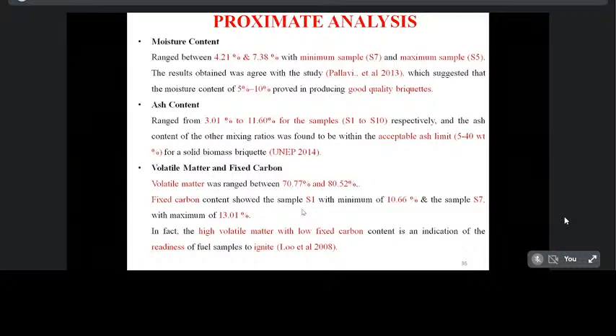sample S5. So the results obtained agreed with the study of Pallavi et al. 2013, which suggested that a moisture content of 5% to 10% proved to be a good quality briquette. And for ash content, the minimum value achieved was 3.01% and the maximum value achieved was 11.60 for sample S7. The ash content of the other mixing ratios was found to be within the acceptable limit that ranges between 5 to 40 weight percentage. Here we are getting only 3.01, maximum value 11.60% for the solid biomass briquette as per the United States Environmental Protection Agency 2014.